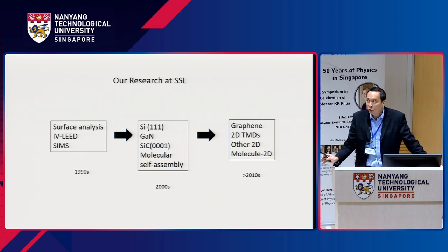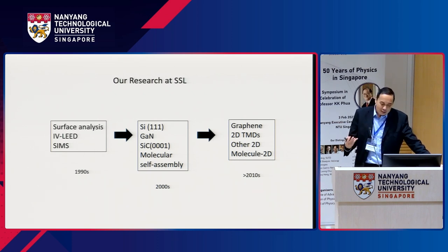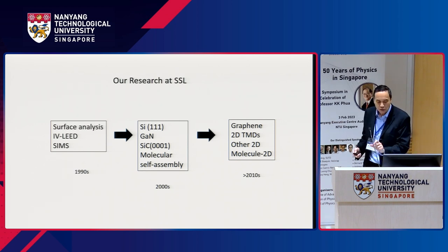Now, Antonio will tell you more about it, but as a surface scientist, I'll have to tell you that our perspective on 2D materials is coming in from a different angle. Because a 2D material is basically all surface and no bulk, our techniques are all relevant, especially the atomic scale techniques. So we started with graphene because by accident, we found out that graphene grows on silicon carbide. And then we looked at other 2D TMDs and other 2D materials, and we also looked at the molecule 2D material interface, as I mentioned before.